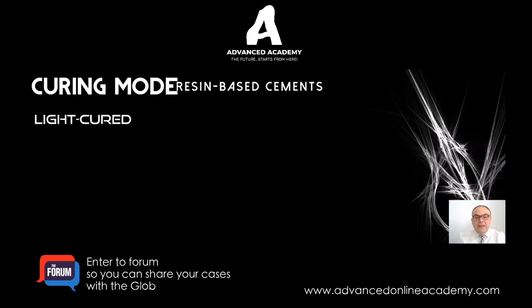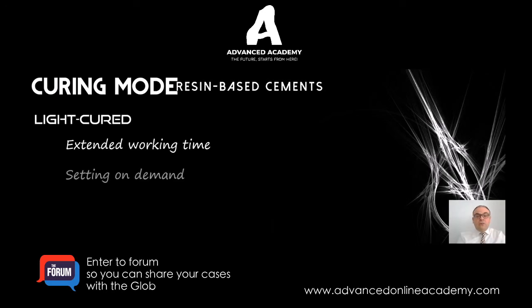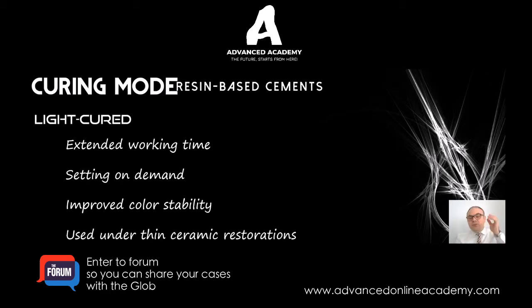Then we have the light cure resins, and so they have an extended working time because they're light cured only. If you don't hit them with the light, they don't set, therefore they're called setting on demand cements. They have improved color stability. These cements do not have the tertiary amine component in them. So therefore, when you're using this cement under a very thin restorative material, like a veneer, you want to use a light cure cement that is stable in color, does not have tertiary amines in them, and therefore they will not discolor with time. Okay, so that's why we use light cure cements only under very thin ceramic restorations.